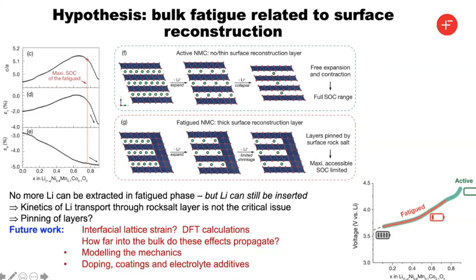So there's definitely going to be an impedance effect, but it's not enough to force the lithiums back in again. It just seems to be sufficient to stop the lithiums coming out at this last point, above 4.2 volts. And what's extremely interesting is that the relationship between the spacings of the rock salt, for example, in a nickel oxide based one, exactly corresponds to the same spacings of the NMC at this 75% top of